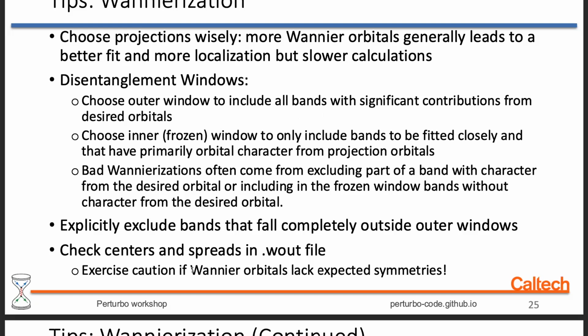And it's also good to look at the output in the wout file and check that the centers are where you expect them to be and the spreads are reasonable. And if the spreads are kind of going crazy or the centers are moving all over the place, that's a case where you should exercise caution.